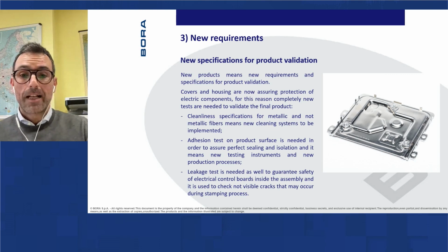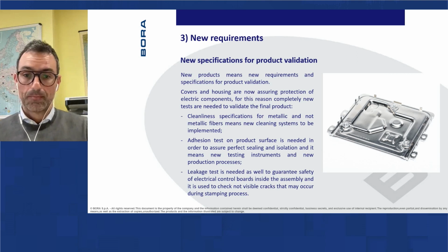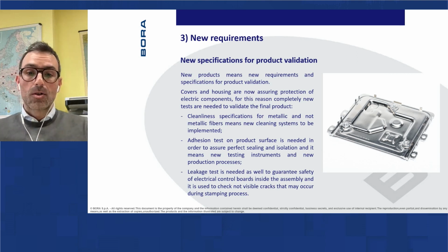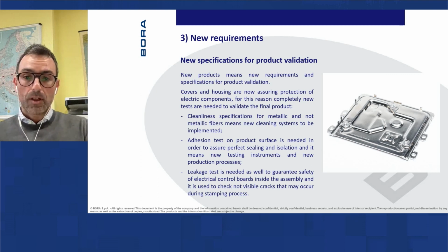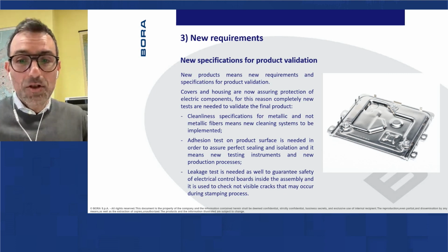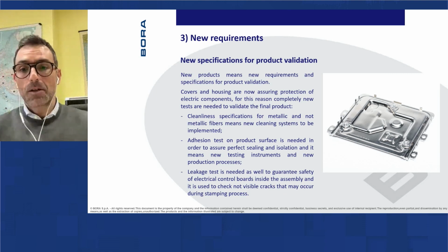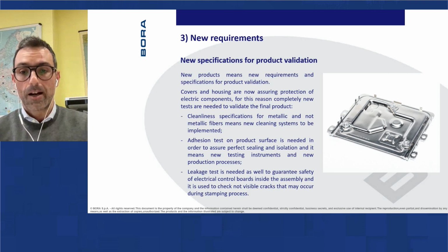Adhesion test is another very important test on the surface, because a clean surface is needed also to have a perfect sealing and isolation. And finally, also the leakage test is performed. I mean that, as I mentioned before, the cracks are very critical in this kind of components, but also the not visible cracks can be critical, because the leakage test is performed with air.